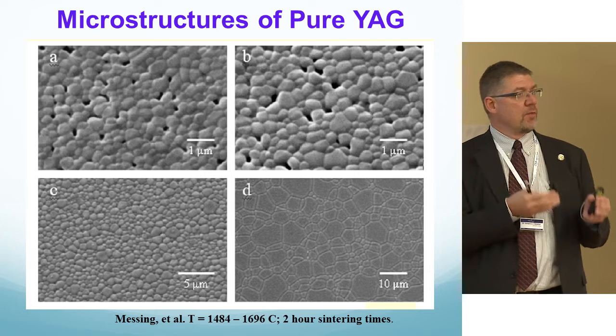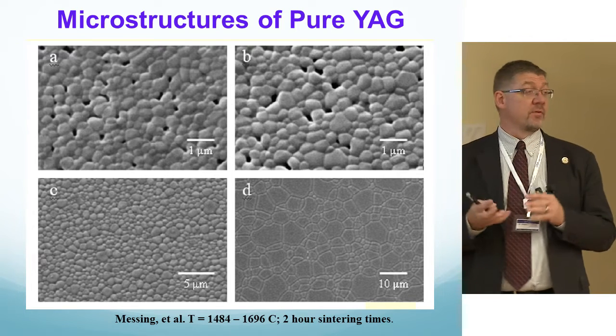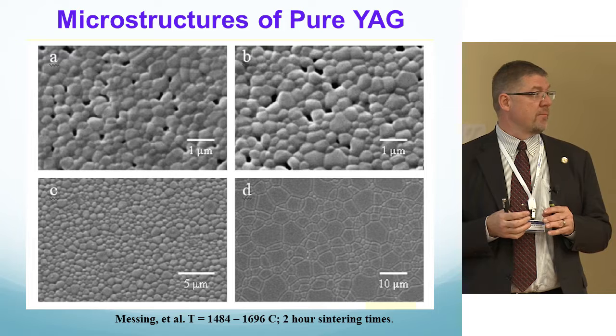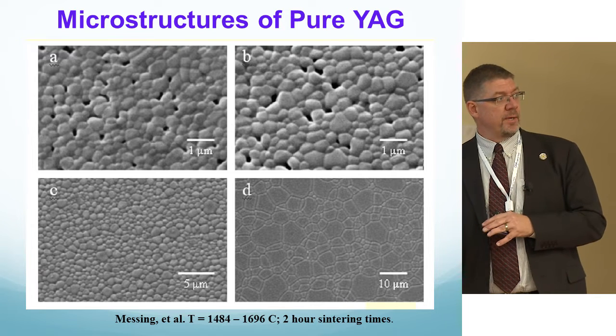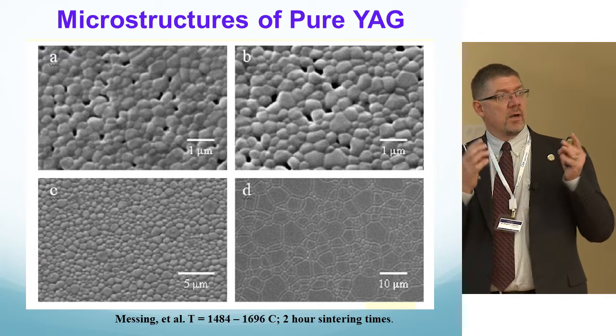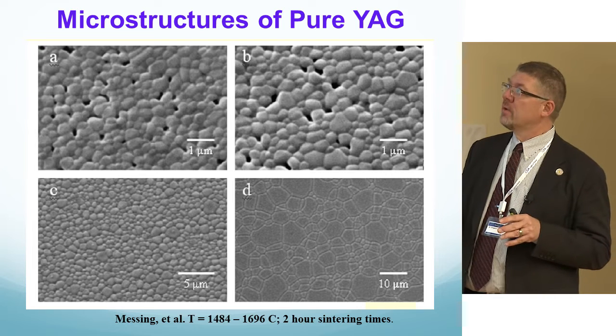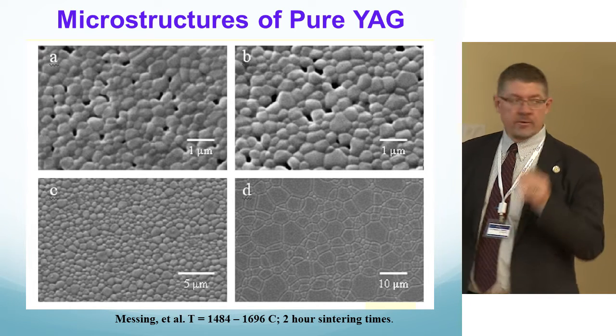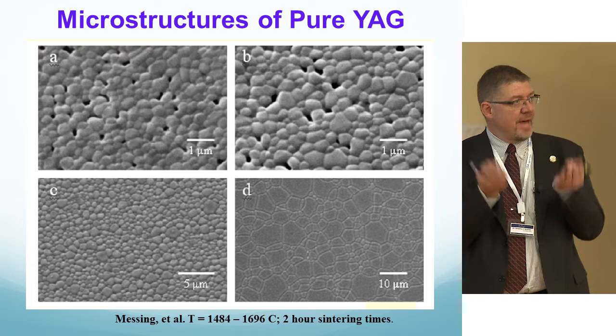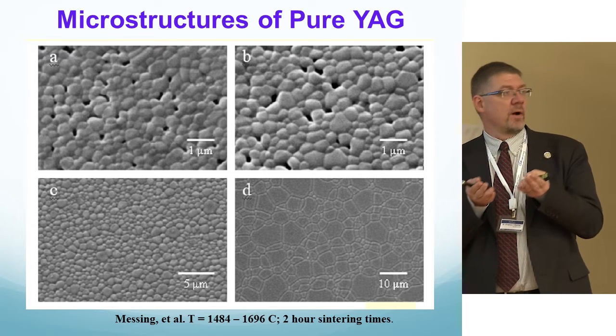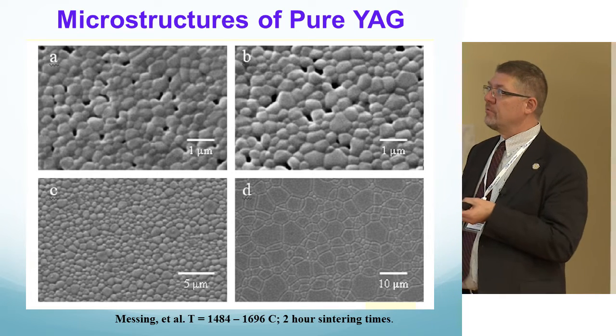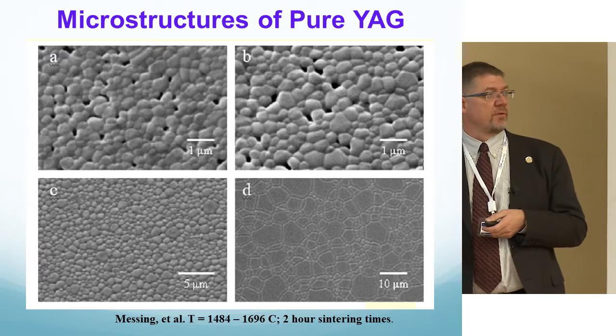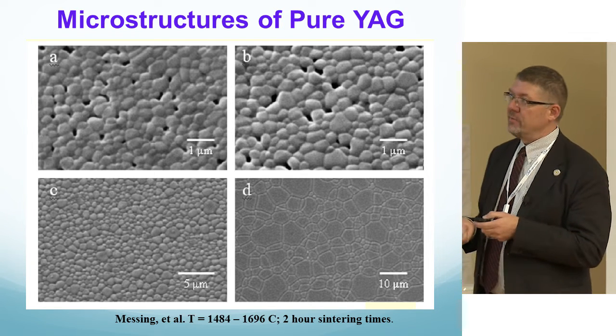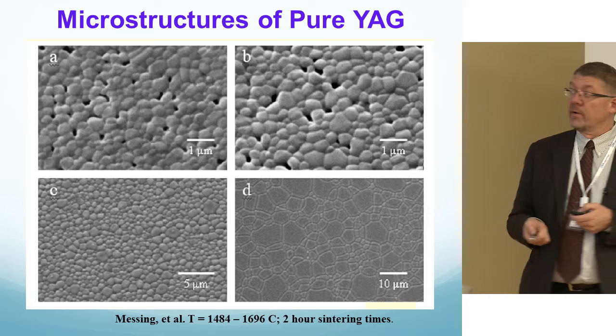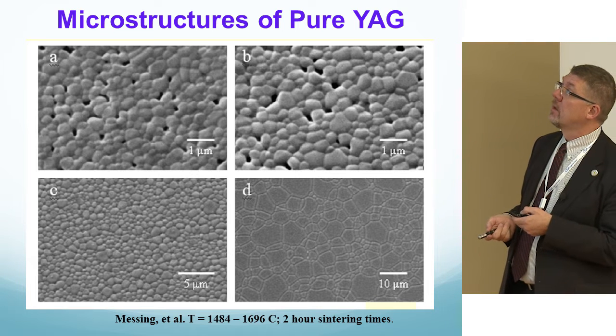So a lot of the work that we spent doing this at our facility over about a 24-month time frame, we funded 3 graduate students' PhDs to really understand what does it take to drive holding the yttrium and the aluminum ratios at the exact right stoichiometry, and what processes does it take to drive zero pores being incorporated into the processing steps. And Adam Stevenson and several others published some very nice theses off of this.